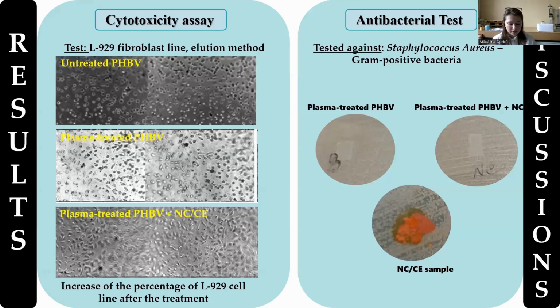The PHBV films were tested further to assess their suitability as dressings. From the cytotoxicity test carried out using the L929 cell line, it was observed that the plasma treatment as well as the plasma and nanocellulose containing curcumin led to an increase in cells, indicating the lack of toxicity and the possible beneficial effect of these types of dressings.